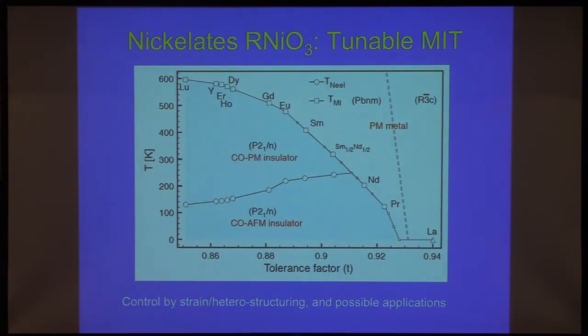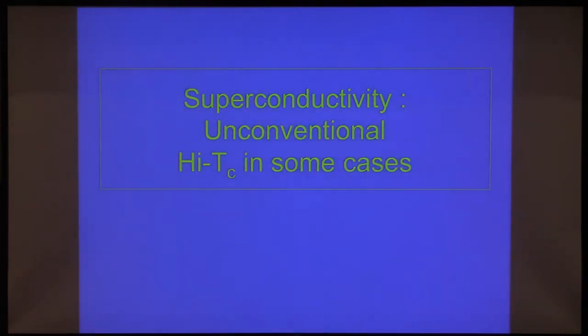This is another set of materials which are transition metal oxides, rare earth nickel oxides, in which this metal insulator transition can be controlled, in terms of the transition temperature, over a very wide range by either doing substitutions on the rare earth site or by applying strain and so on. You'll see more of this in the rest of the talk. Okay, so these were MITs.